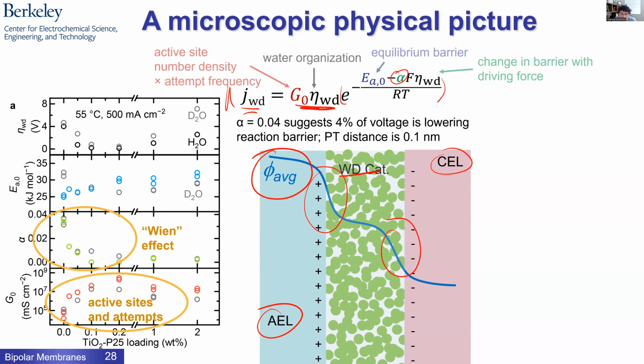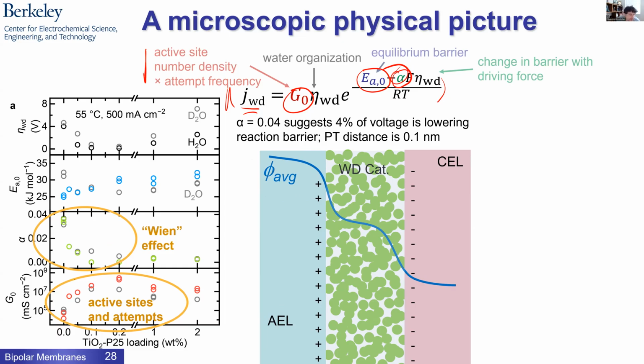Now, typically in electrochemistry, this is a constant or related to the reaction, but here we've actually split this into two terms. A term that we're going to call G naught. It's going to be related to how many active sites there are for dissociation and some sort of attempt frequency. And then we're going to multiply that by, again, the driving force. So the driving force must affect the prefactor in some way, and this is the simplest way to do that. So now we have three parameters to fit every single temperature-dependent, loading-dependent piece of data I showed you. And when you do that, you can see some very interesting things.